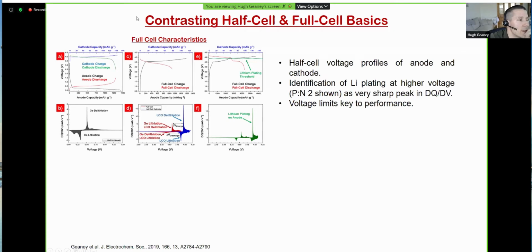So in terms of contrast in half cells and full cells, these are our results from the paper. These are our half cell cathode cycling, and this is our half cell anode cycling, and this is our voltage profile then for our full cell charge and discharge. So this is for a germanium and LCO full cell. What we found is the voltage window is very important in this case. So this is for a full cell that had quite a large cathode excess. So there was more capacity on the cathode side than could be accommodated on the anode side.